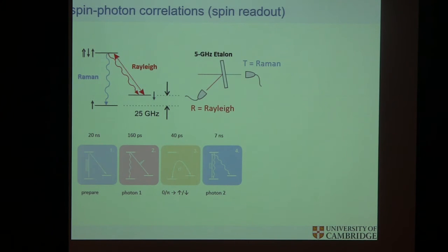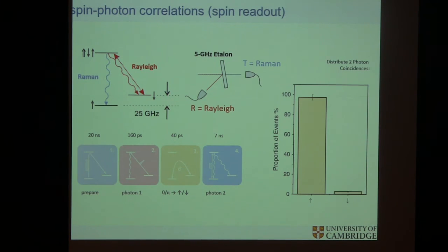That ultimately gives you a change of time scales. Anyways, let me go through this part. Once you detect the photon and don't know where it came from, you want to go back and check what the spin state is. For a single quantum dot, we can find a correlation between the internal state of the quantum dot and having detected a photon, whether it's still down, because we didn't see a photon, or up when we did see a photon. If you do that experiment, then that also puts a below 100% limit. That's another prefactor that will be multiplied, minus 7%.